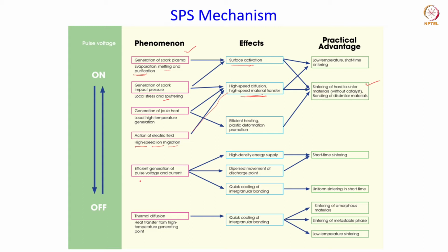Efficient generation of pulse voltage and current, and its effect you can see in terms of high density energy supply, dispersed movement of discharge point, and another effect is quick cooling of intergranular bonding. And this quick cooling is good for uniform sintering in a short period of time. And then there is thermal diffusion due to heat transfer from high temperature generating point, and this leads to again the same effect, the quick cooling of the intergranular bonding.